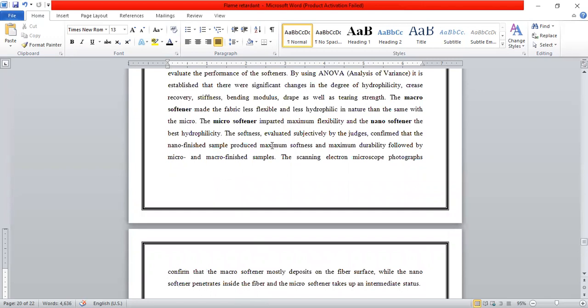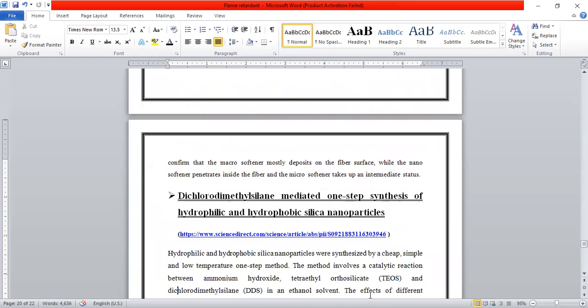The softness evaluated subjectively by the judges confirmed that the nano finished sample produced maximum softness and maximum durability, followed by micro and macro finished samples. The scanning electron microscopy photographs confirmed that the macro softener mostly deposits on the fiber surface, while the nano softener penetrates inside the fiber and the micro softener takes up an intermediate status.